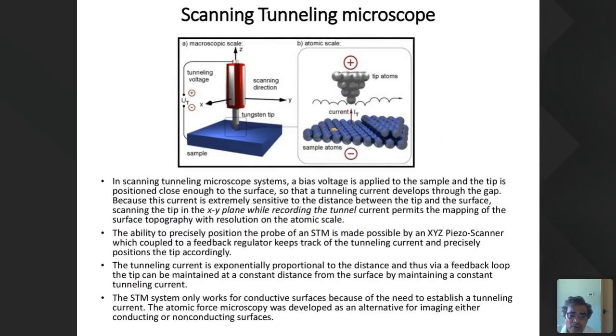Let us see how the scanning tunneling microscope works. You can see the picture here. It is an enlarged picture of this tungsten tip when it is near the sample. So there is a scanner, which gets feedback from the sample. In a scanning tunneling microscope system, a bias voltage is applied to the sample, and the tip is positioned close enough to the surface so that a tunneling current develops through the gap. That means the tunneling current develops between the very sharp tip and the sample. It does not touch exactly; there is some gap. Because this current is extremely sensitive to the distance between the tip and the surface, scanning the tip in the XY plane while recording the tunneling current permits the mapping of the surface topography to resolution on the atomic scale.